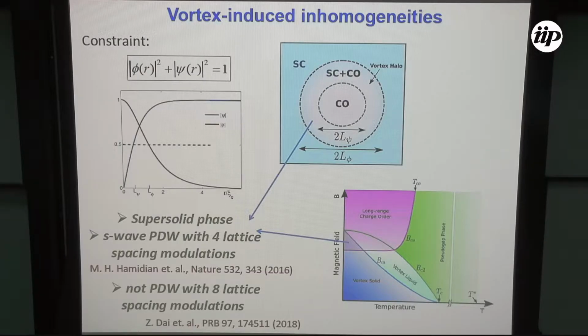Interestingly, there would be a region around the center, which is called the vortex halo, where you can get a coexistence phase of charge order and superconducting order. And this was also seen recently in STM measurements. If we increase the field, these halos will condense, and in this portion of the phase diagram, we can say that there is a possibility they will form a PDW phase with the same lattice spacing modulations as the charge order phase.